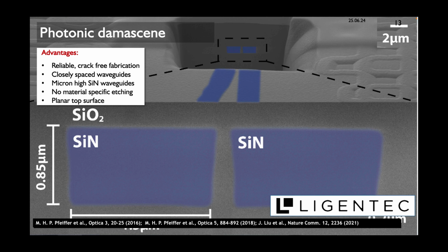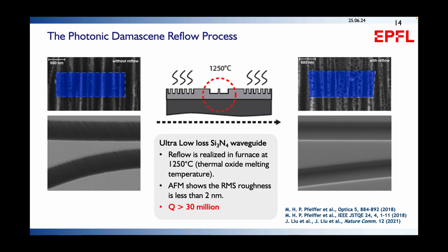Now, to create waveguides with exceptionally low loss, we use one more trick. And the trick we use is that glass, in contrast to silicon nitride, starts actually to soften at 1200 degrees. So we can take the preform of glass and just heat it up to glass softening transition, and thereby actually take out all the roughness actually from the etching. And this way we can make waveguides that have exceptionally low loss.